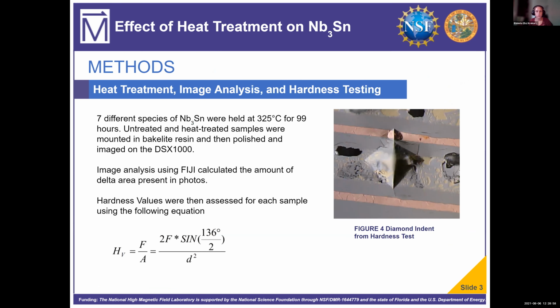And so in our methods, we took 7 different niobium-tin (Nb3Sn) species and put them in a furnace for 325 degrees Celsius for 99 hours. And then after that, we took the untreated and heat treated samples and metallographically prepared them for imaging. We used the DSX 1000 to take pictures, and then used Fiji to analyze and visually inspect the phase present in our samples. And then after that, we used the following equation and a Vickers micro hardness tester to assess the hardness values for the pre and post niobium-tin (Nb3Sn) samples.